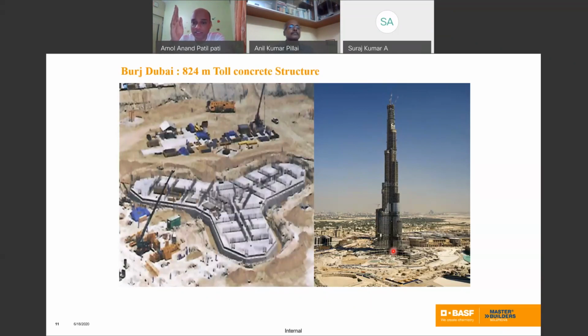This is the challenge. Is that clear? The hydrostatic pressure of a 824 meter vertical column of concrete in the pipeline carries the hydrostatic pressure, and that hydrostatic pressure acts back onto the pump. Then it creates hoop stresses. Hoop stresses act on the periphery of the pipe wall, and there are chances of bursting of the pipeline because of the high hydrostatic pressures. So this is the challenge: how can we design the concrete to pump 824 meters high?